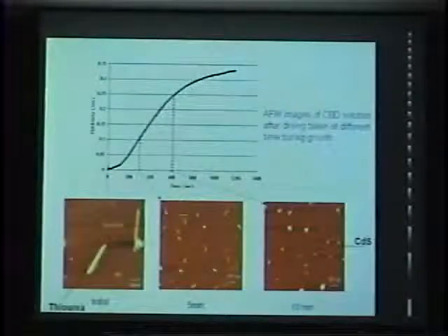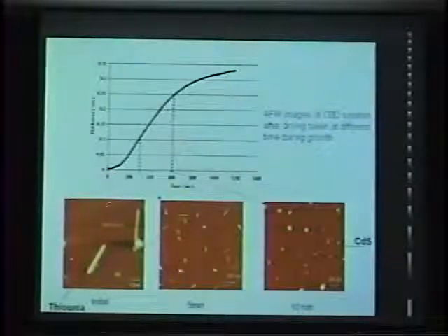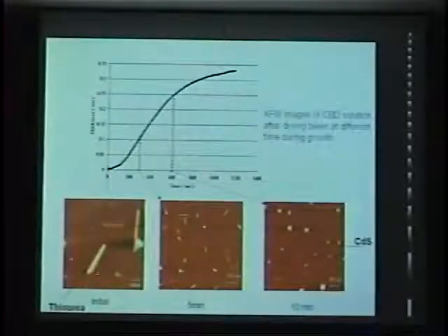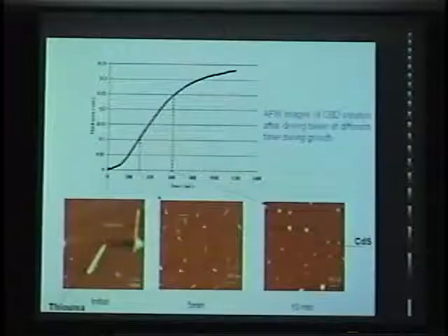So this just shows some. If you take the solution out and drop it on, for example, a silicon substrate, you can see these after the solution dries. You see this is thiourea. That's kind of interesting. This actually means the thiourea is not being consumed initially, right? So then when the solvent is gone, you have this thiourea crystallized.